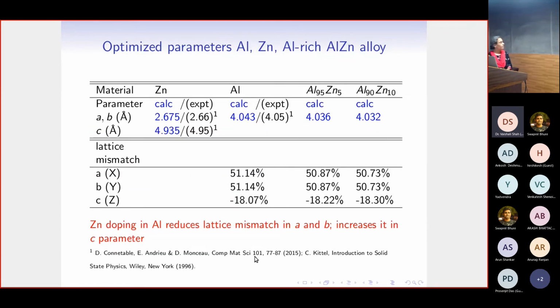So with this, then when we do the total energy calculations, optimizations with respect to the lattice parameters, then we compare what is our calculated lattice parameter and how it compares with what is reported in experiments. So the figures in blue are the calculated ones, and the experimental one we have put in the brackets. So you can see that this comparison is very good. So for zinc, for aluminum, both of them, the comparison is very good for the A and the C lattice parameter.